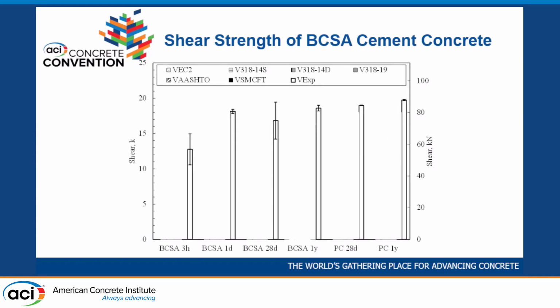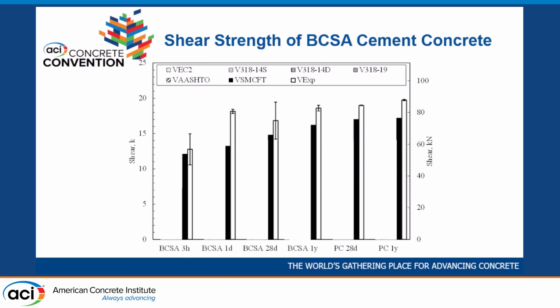We compared these capacities to all the code equations. Portland cement's over here, tested at 28 days and 1 year. BCSA we tested at 1 year, 28 days, 1 day, and 3 hours. These are all the average of 2 different beams, so there's a little bit more variability in a couple of these BCSA ones. We compared these to the modified compression field theory in AASHTO. This is the best existing equation to calculate the shear strength of concrete, and you can see it calculated the strength of the Portland cement with similar conservatism as the BCSA cement, more or less.